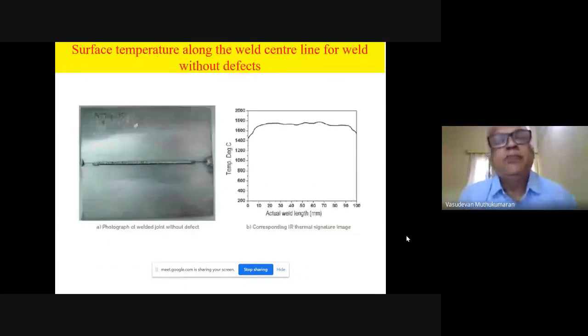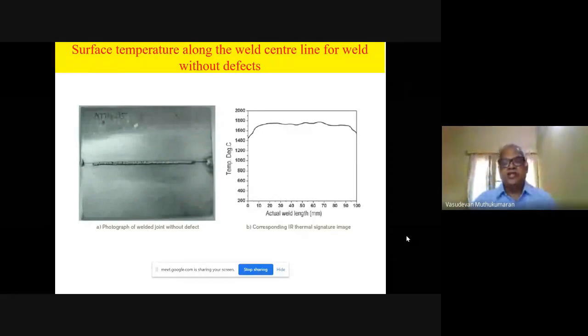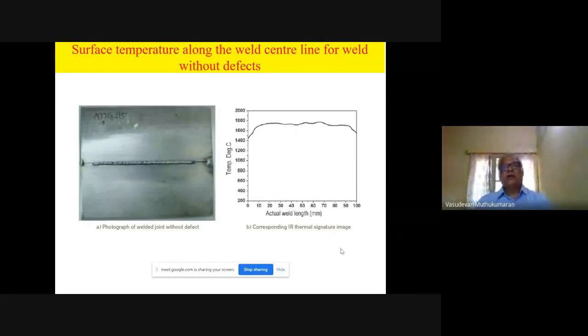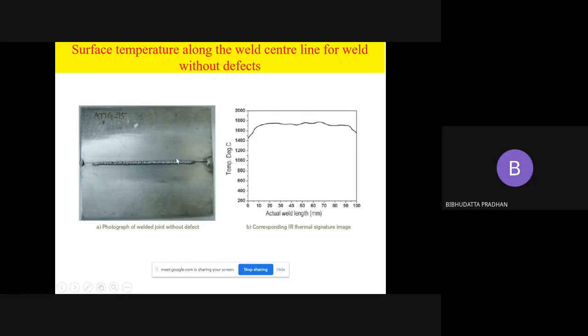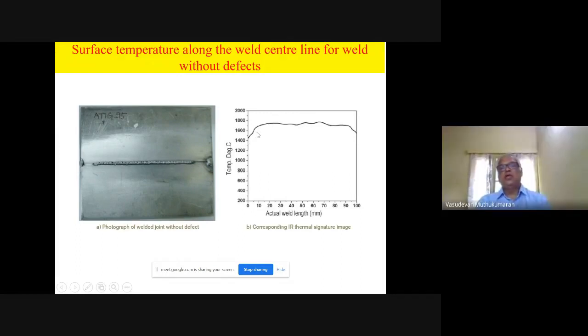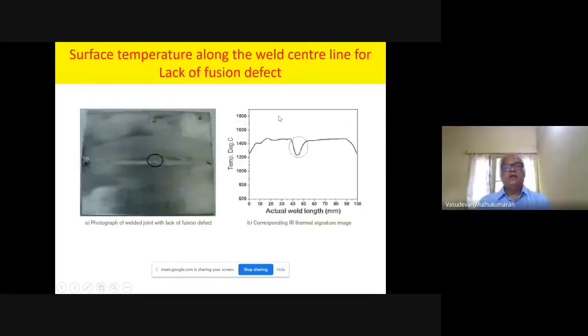We can see some of the image signatures we captured using the IR camera. You can see this entire weld length. We measured the temperature for the entire length, and we can see that it's almost flat. So it shows complete penetration. It's the backside of the weld. When you get a complete penetration, there is no change in the temperature; it is almost the same. Suppose when you measure the surface temperature, there is a defect like a lack of fusion, artificially introduced. That is reflected in your signature image.